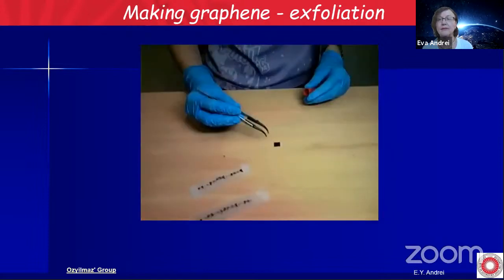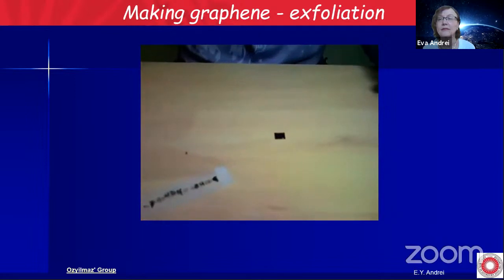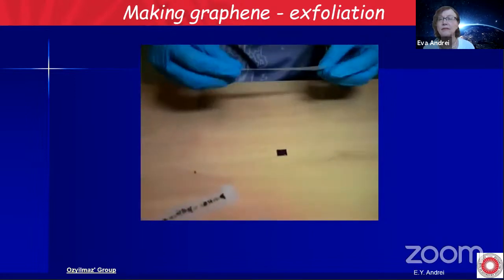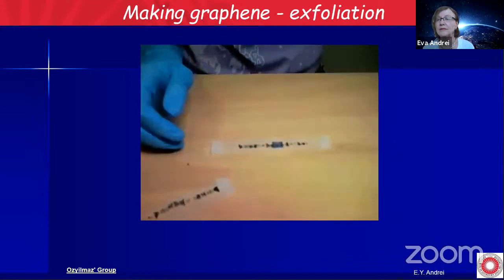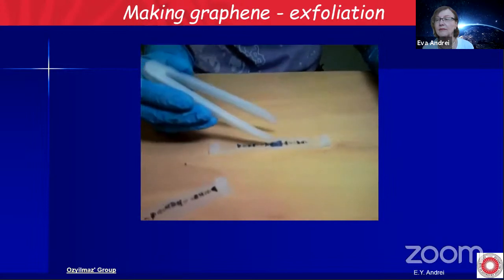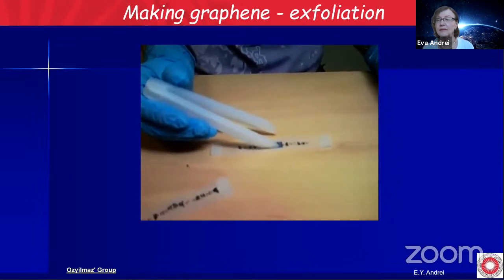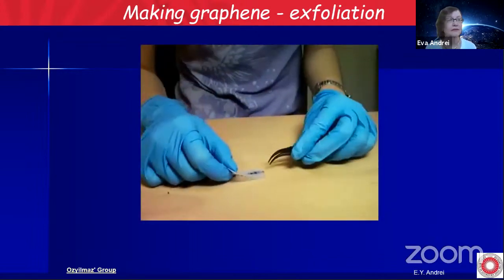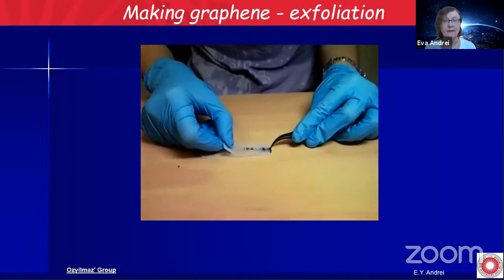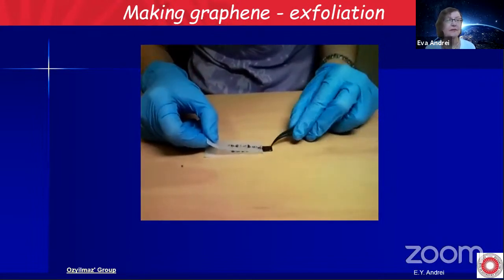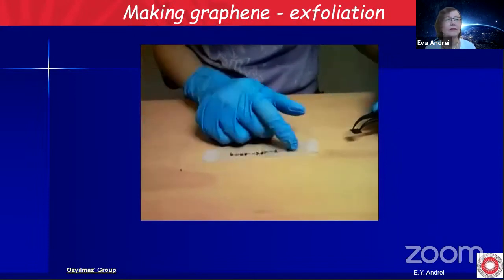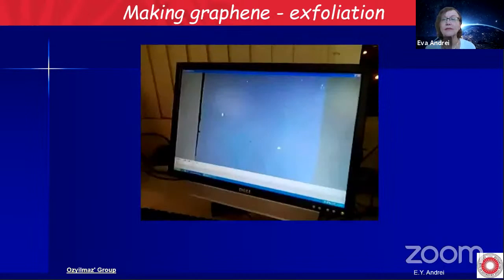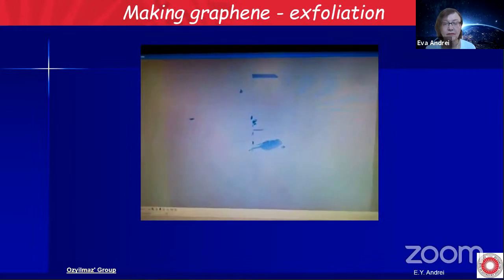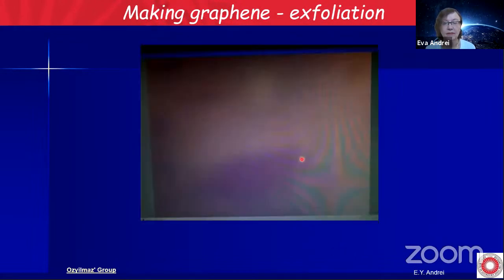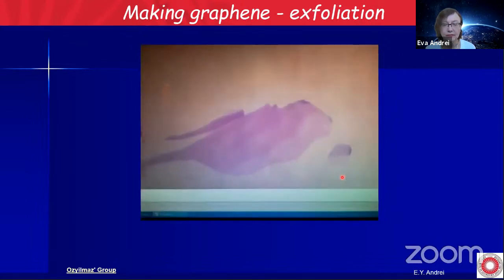After this, take a clean silicon wafer to transfer the Scotch tape graphene onto the wafer. Use plastic tweezers and gently rub the area of the Scotch tape where graphene may potentially be. Slowly peel off the Scotch tape so as not to break any potential graphene sheets. Use an optical microscope to view and find graphene. Graphene appears as purple spots on the screen. At the center of the screen is multi-layer graphene, and at the lower right corner of the screen is single-layer graphene.